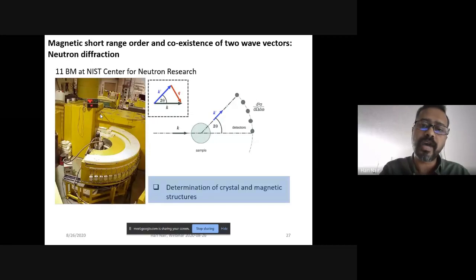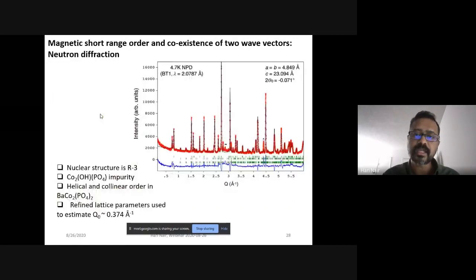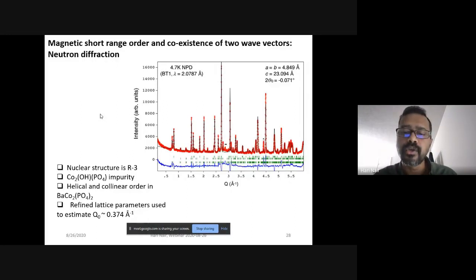So we know the value of K, we know the value of K prime, and we know at what angle the detector is. The detector just measures clicks. When a neutron comes and hits it, you measure a click. With this information, you can determine crystalline magnetic structures. The data that you get out of it looks like this. It's very similar to an X-ray diffraction pattern, and you have intensity as a function of Q, which is K minus K prime, in inverse angstroms.